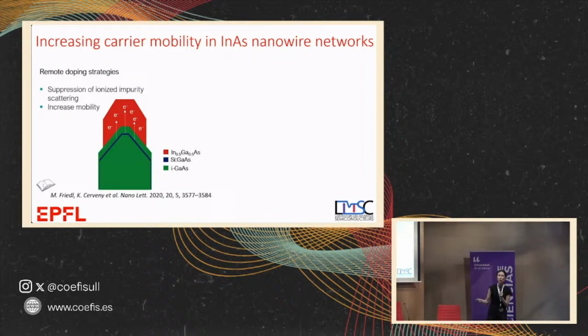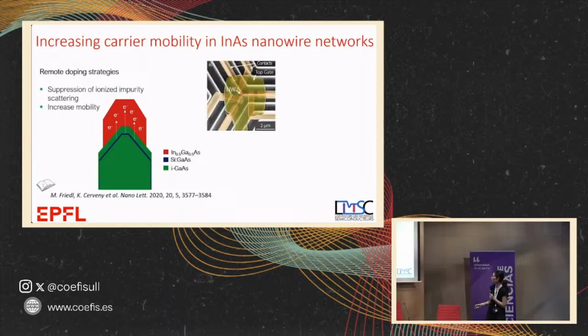So what we did is we make a trick that is not ours, has been used for a very long time: you dope the base where the gallium arsenide is, and then create electrons that want to go here because this is a lower potential, lower band gap, and so they all will accumulate here without having the dopant. So the dopants stay here. If you would have electronic transport here, it would perturb, but as they go here, you can have, in principle, the highest mobility of indium arsenide without having to dope the indium arsenide.